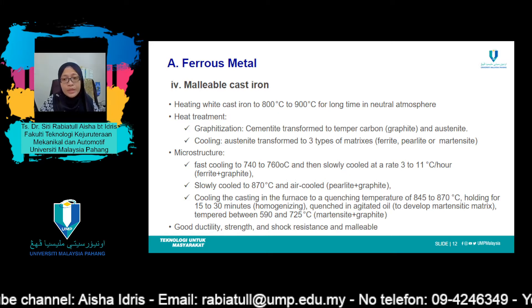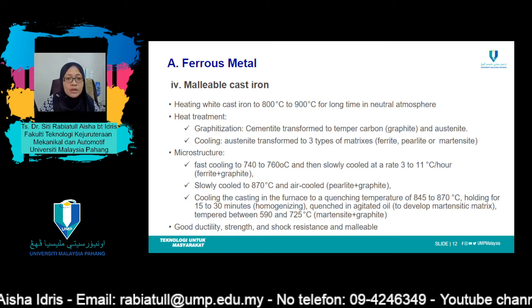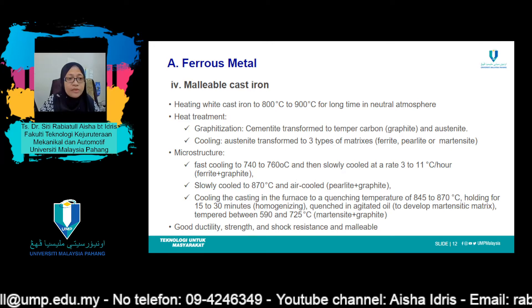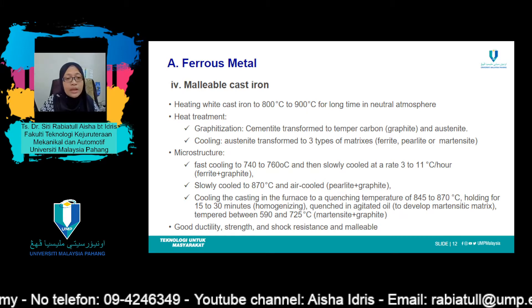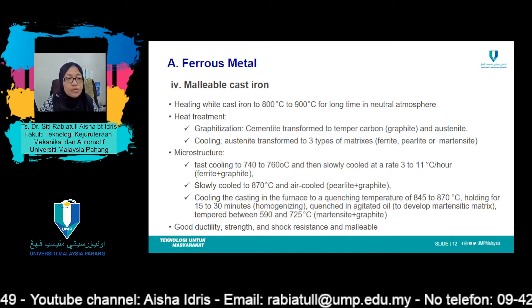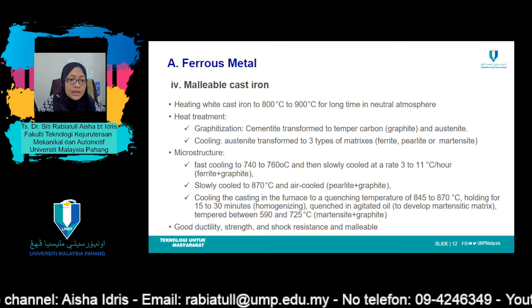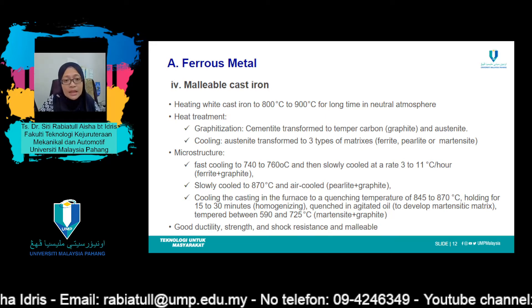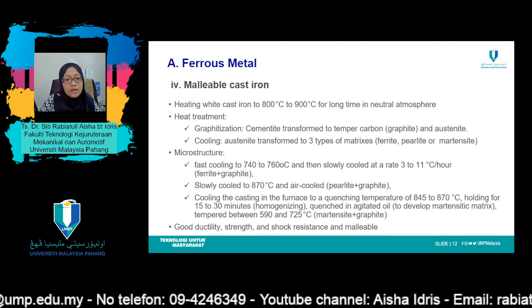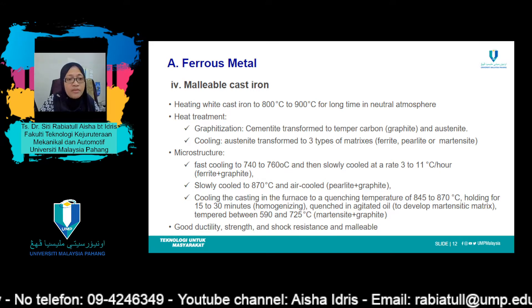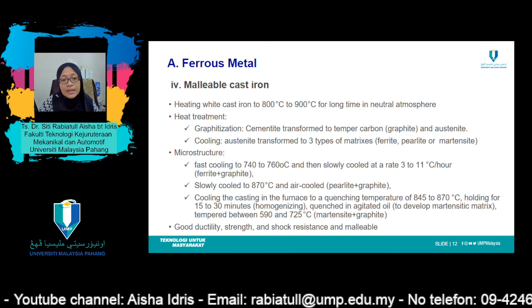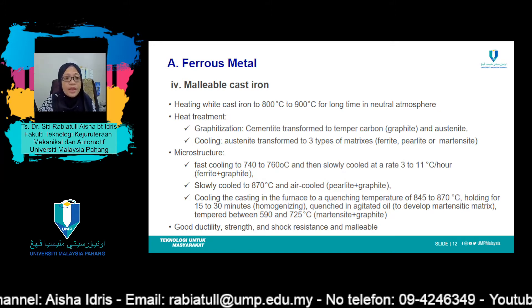Heating white iron at temperatures between 800 to 900 degrees C for a prolonged period of time in a neutral atmosphere causes decomposition of the cementite, forming graphite which exists in the form of clusters or rosettes surrounded by a ferrite and pearlite matrix depending on the cooling rate. The microstructure is similar to that of nodular iron, which accounts for relatively high strength and appreciable ductility or malleability. Representative applications include connecting rods, transmission gears, refrigeration cases, flange pipe fittings, valves, and other heavy-duty services.